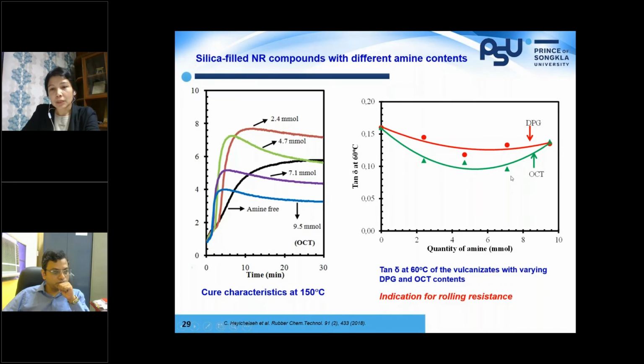By comparing DPG and octadecylamine, based on different properties, we select octadecylamine as an alternative, and we vary the quantity of octadecylamine in comparison with DPG in order to see whether we can find the optimized content. And based on various properties, tan delta at 60 degrees is chosen as an example here. We can see a drop in tan delta at 60 degrees, which we use to indicate rolling resistance. We can have even lower tan delta